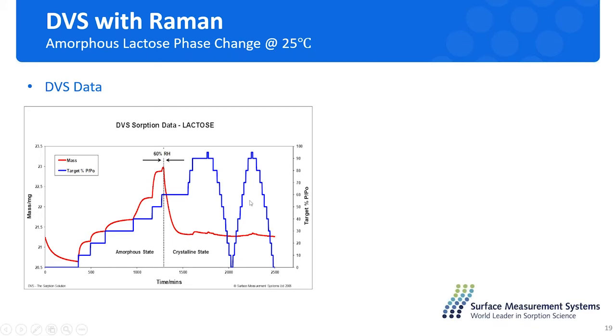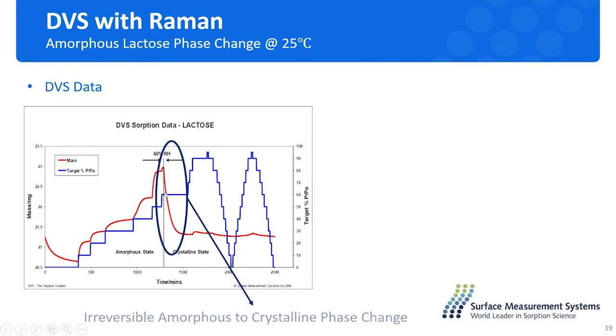Here's an example with the amorphous lactose sample. Here's the DVS data we are getting. The blue line is the target relative humidity at each stage. We are changing from 0 to 95% RH in different steps. And the red line is the change of mass for the sample. Whenever we introduce the humidity to a different level, it will pick up very quickly and then reach a final equilibrium state. But you will notice at 60% RH here, the mass is not increased anymore, it drops a lot. That's because of the amorphous to crystalline phase change of this amorphous lactose sample. And this change doesn't happen in the second cycle, so it's basically an irreversible phase change happening here.